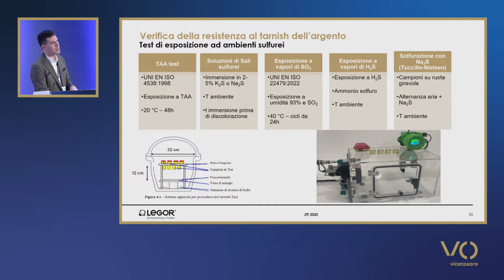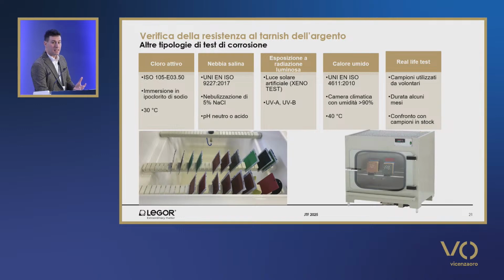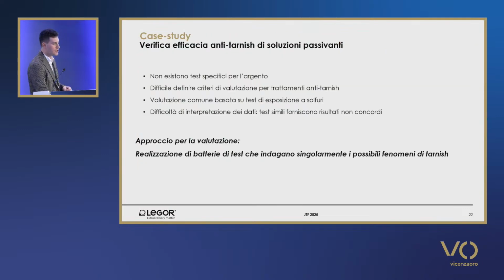The most frequent tests are those where the silver surface is exposed to sulfur. It can be vapor, or immersion in solutions, sodium sulfide or potassium sulfide. Now, it would be appropriate also to check the resistance of these objects, exposing them to other compounds, whether it's chloride, or humidity, or ultraviolet radiation. It would be interesting to carry out a real-life test for all the possible complex situations.